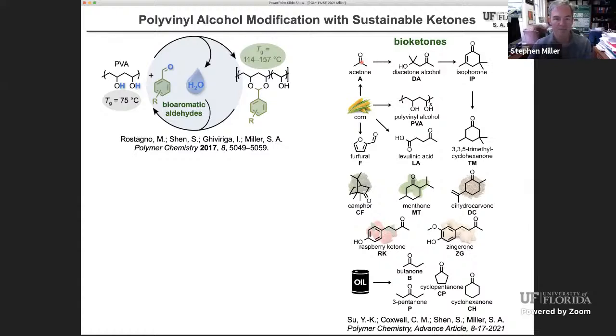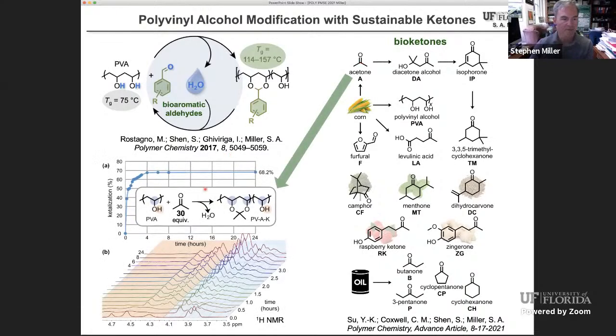So as I mentioned, we attached many of these to polyvinyl alcohol. Here's a waterfall plot of, again, a closed NMR system, where in the presence of 30 equivalents of acetone, we get about a 68% ketalization. That means 68% of the OH groups are now occupied by ketones. It's a ketalization process, and some 32% of them remain unattached to acetone.